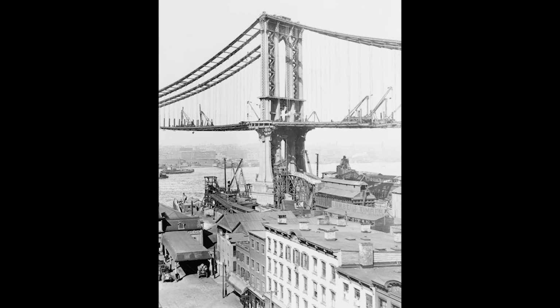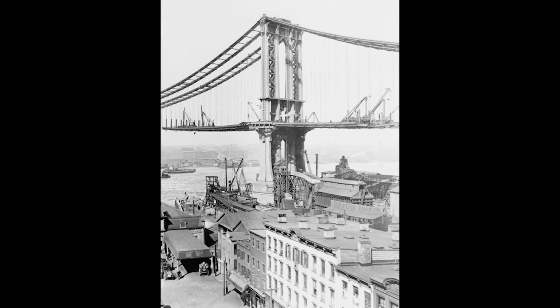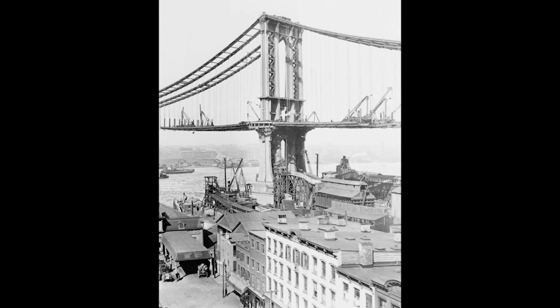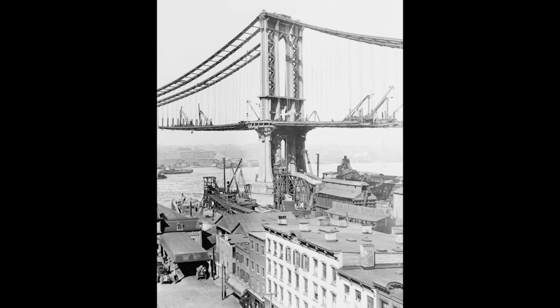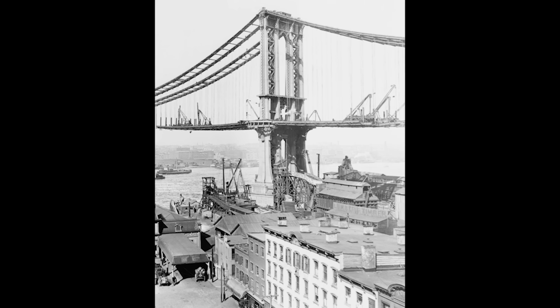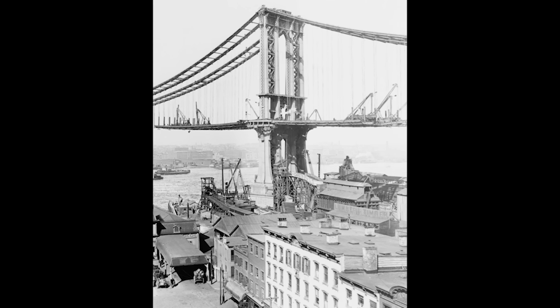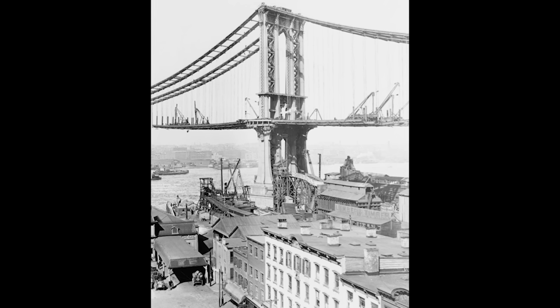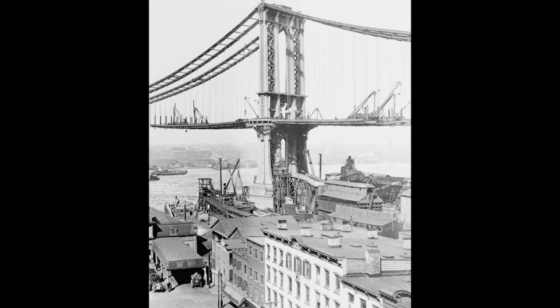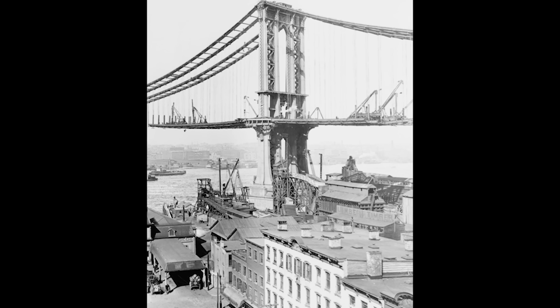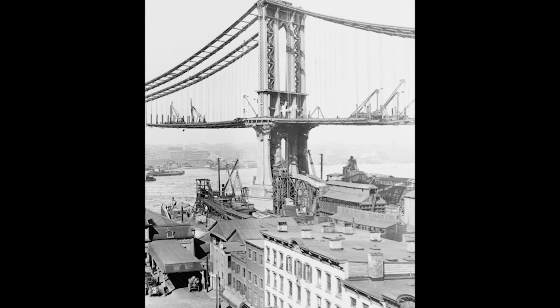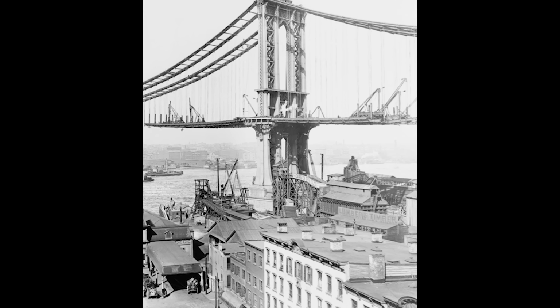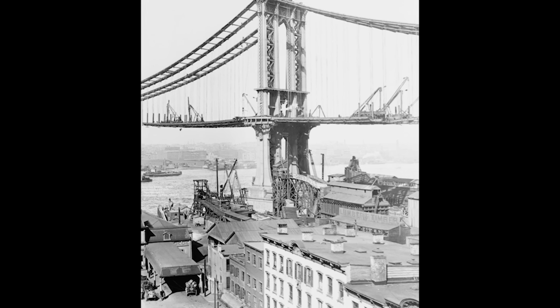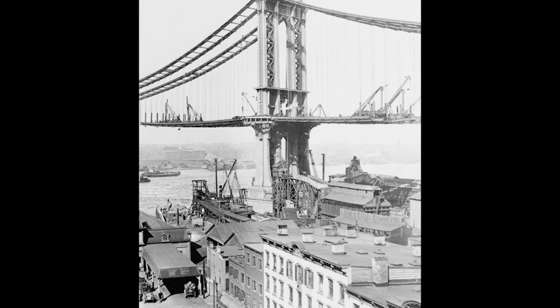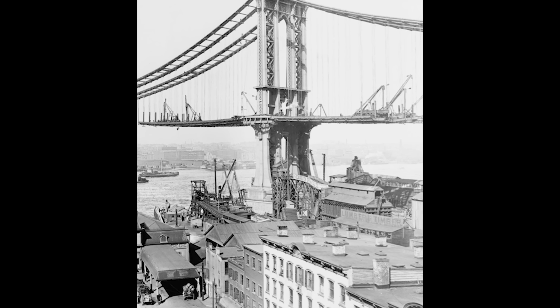The cable cross-section revealed the systematic logic of Roebling's protective philosophy as each layer was applied. The galvanized structural wires provided sacrificial protection at the steel surface through zinc's electrochemical properties. The galvanized wrapping wire eliminated physical gaps where moisture could accumulate against structural elements. The red lead paste sealed microscopic voids and provided chemical resistance to corrosive compounds. The multiple paint coats created a weatherproof outer shell that shed water and resisted atmospheric attack.